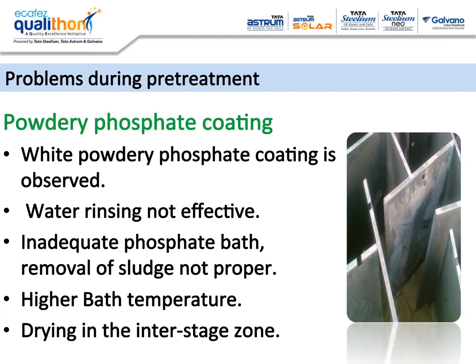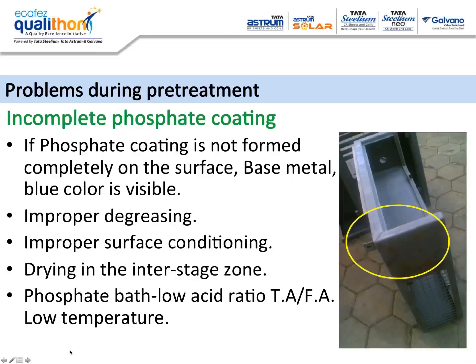And sometimes, as I think Mr. Mahendra Rawat was saying, people will scrub it with something and then there'll be a problem. You are removing the phosphate layer, number one, and you're doing a lot of handling, so probably you are contaminating the surface again. So that is also not a very good condition.